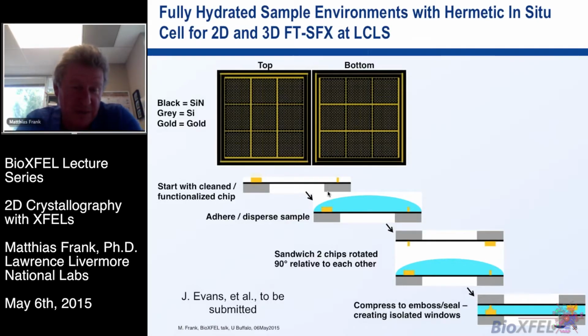Of course, you might also be interested in having a fixed target measurement on a sample that is fully hydrated. Our colleague James Evans, who is now at the Pacific Northwest Lab, has developed a technique that does exactly that, and it's essentially two of these wafers with thin membranes just put on top of each other with little spacers in between, and in this case they're gold spacers. So you have a bottom wafer, a silicon nitride membrane, there's some lines of gold on top of it, you put a sample down in a liquid solution, and then you take another piece, turn it around, and put it together. And what you produce is individually enclosed compartments of sample.